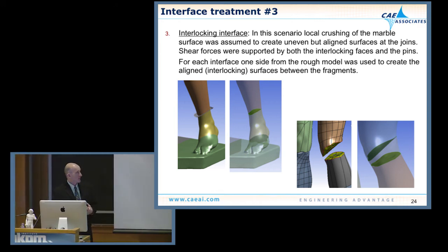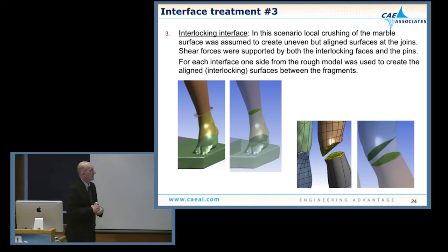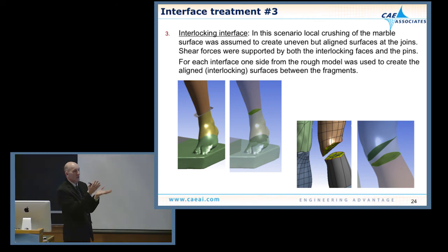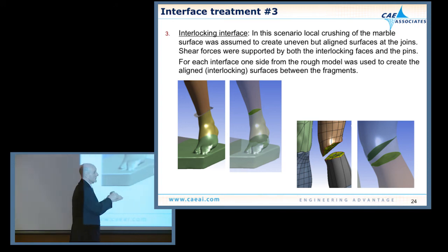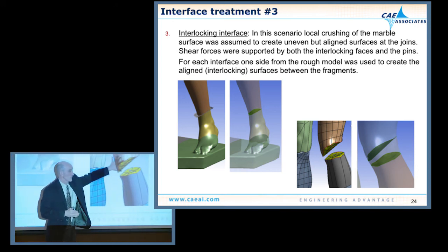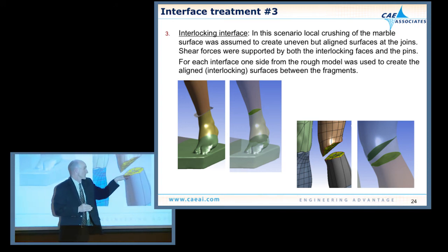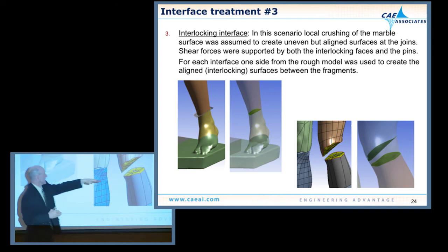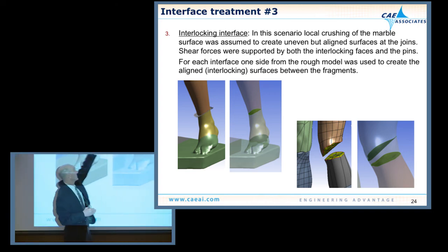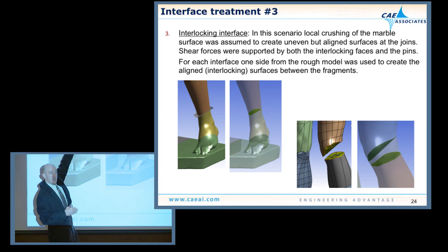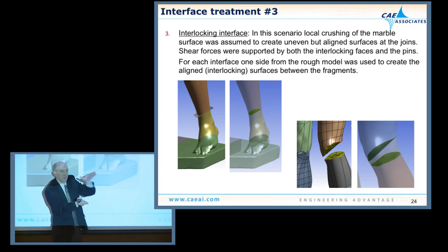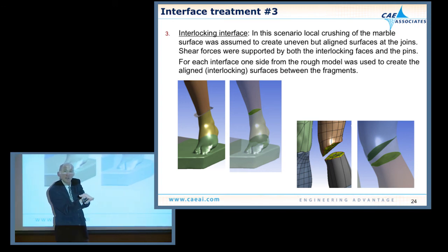And then the final interface treatment, this is kind of the middle bound area. This was our attempt to get as close as we could to what may actually be occurring at the interface. And that was to make an interlocking interface between the two fragments. The way that we did that was to take the surface from the broken piece, bring that into the homogeneous model and use it as a cutting surface. In doing so, we made two uneven surfaces that were aligned and interlocked.